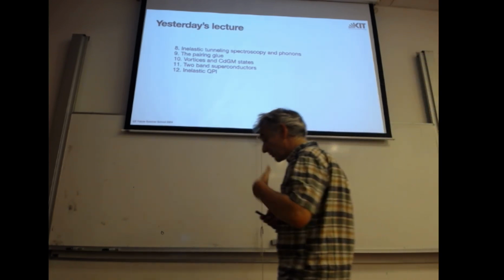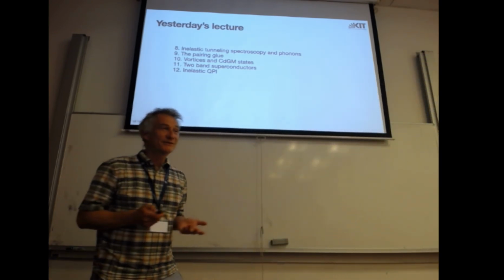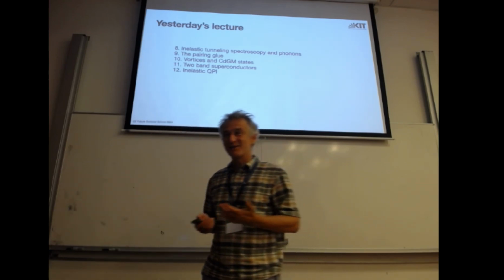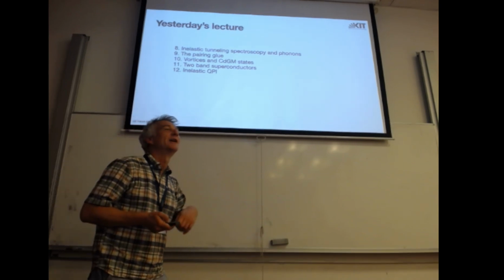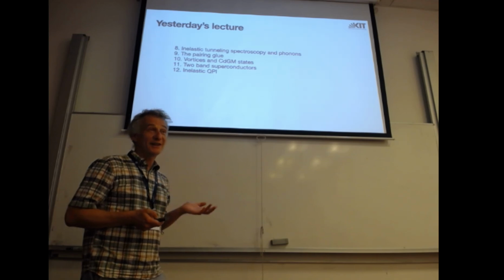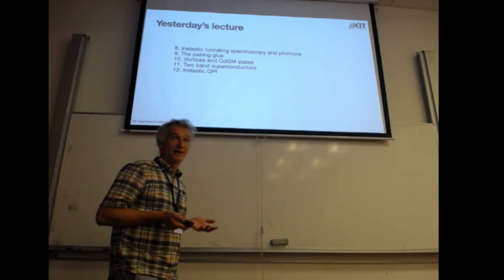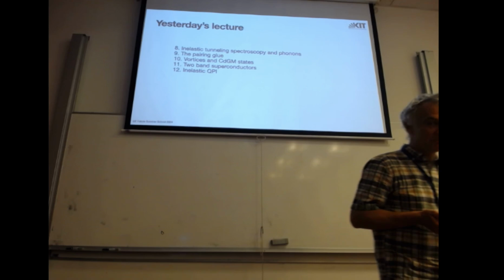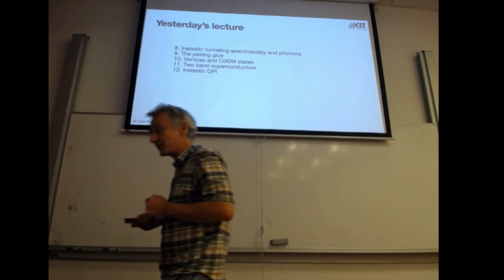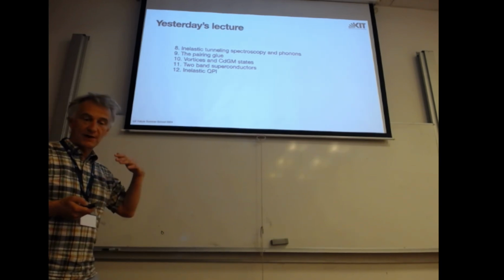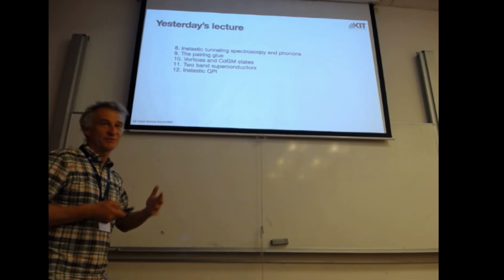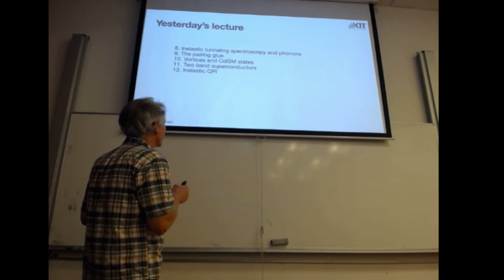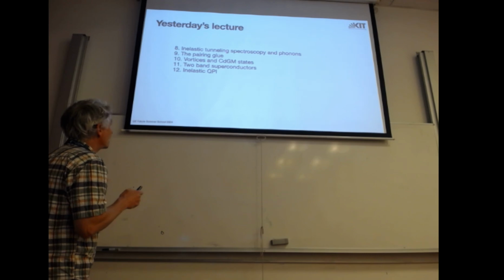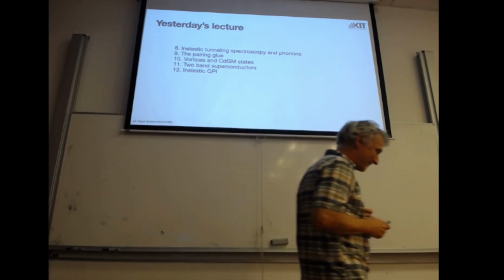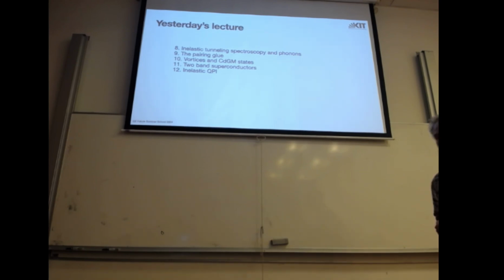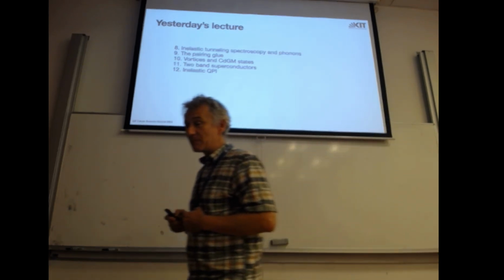You can also look at that from a different point of view. If you take a naked electron, it's not really naked, but it's already renormalized due to the potential in which it sits and the electron-electron interaction. Now you also add the phonons, so this electron will be dressed with phonons and changes its mass and also its lifetime. It also contains the information about electron-phonon scattering. Then this inelastic tunneling is actually just elastic tunneling due to this modified spectral density of the electrons. That brought us to the insight that inelastic tunneling has to do with the Eliashberg functions, and then maybe we can measure it.